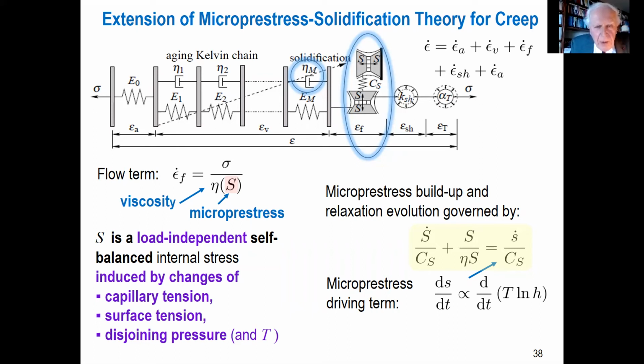There were, in computational mechanics, several models published in the area of nuclear reactor research, which did not take into account this thermodynamic restriction, and they actually violated the second law. So that restricts the form of the power law. Then to model over a long scale, you need a broad spectrum of relaxation times ranging from microseconds to years to decades. So we need a Kelvin chain to describe it, much more effective than integrals. And eventually there's one element which has a very small elastic resistance, basically flow.